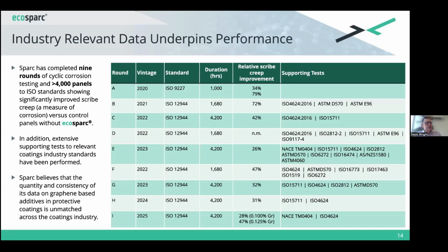The other part of that is you can see we don't shy away. We don't put up, oh, it's wonderful every time. We've got a heap of good, consistent data there, and there are variations in it a little bit, and some of that is due to the coatings that it's put in, and some of that is due to the extent of time. There's a couple there that people will see that are 1,000 hours, not 4,200. It's a slightly shorter test. You get a slightly different set of results, and you're looking for different things. But overall, we get good, consistent data with significant improvements in scribe creep and corrosion resistance.